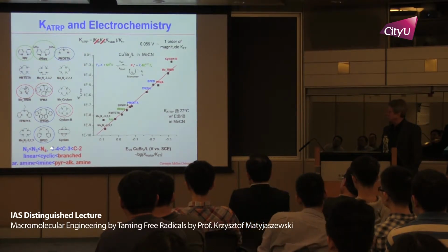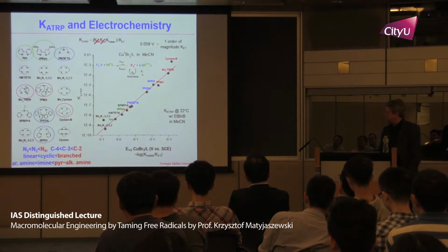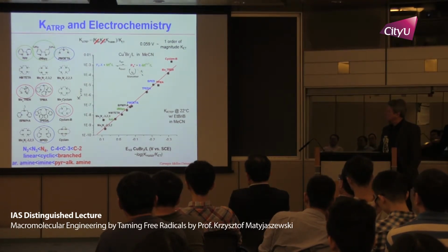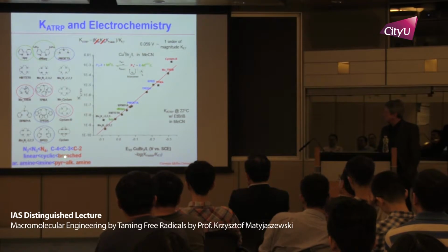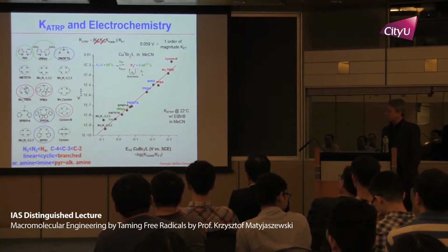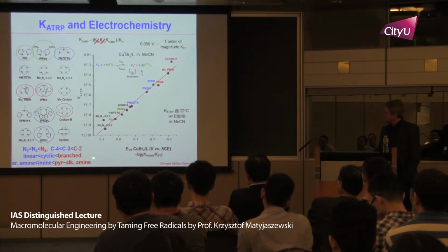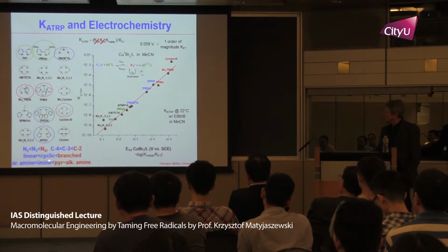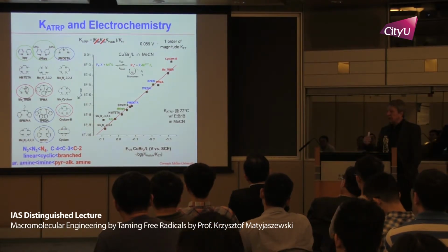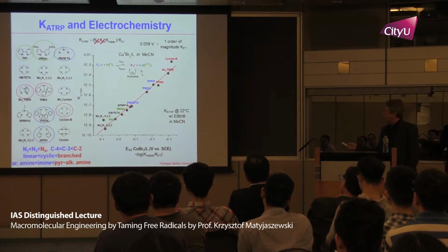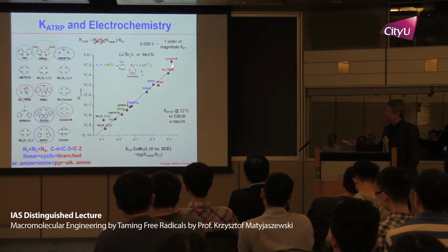nitrogen atoms. 4 is better than 3, which is better than 2. For the bridge between nitrogen atoms, 2 carbons is better than 3, which is better than 4. Branched structure is better than cyclic and linear. As for the nature of the nitrogen atoms, alkylamines and pyridines are much better than imines or other amines. So these systems circled in red are really the best of the best, and they are more or less positioned here.